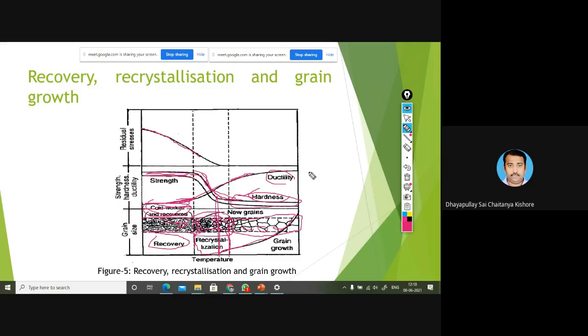That's why, if you want to decrease the strength and hardness of a work material, people prefer the annealing process. It is a heat treatment process. By performing annealing, you can reduce the strength and hardness of the metal. So that is related to recovery. Recovery occurs below the recrystallization temperature of the metal. During this, the stresses in highly deformed regions are relieved. And recrystallization is the process in which, at a certain temperature range, new and strain-free grains are formed.